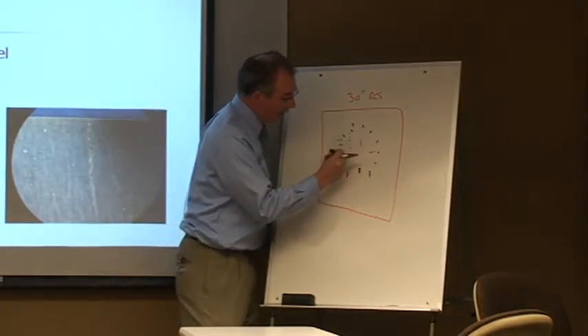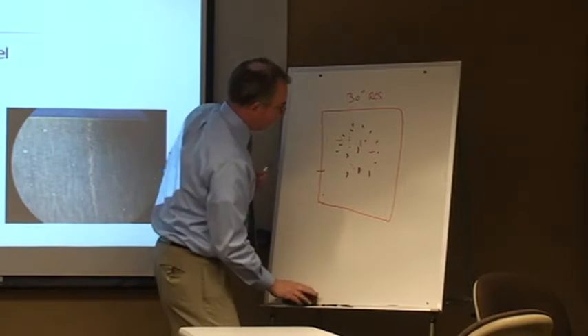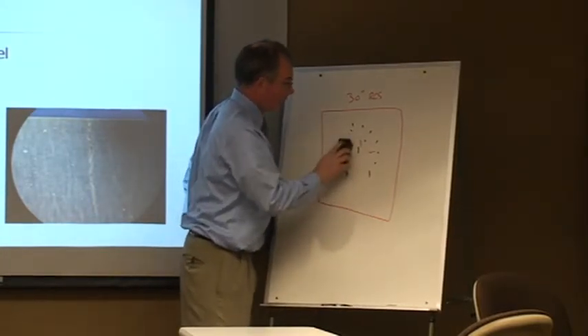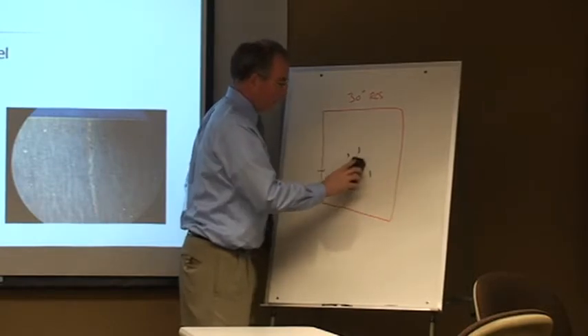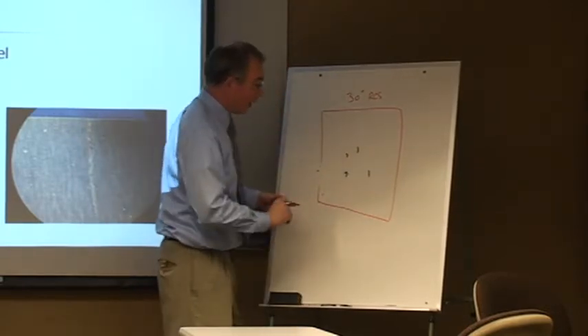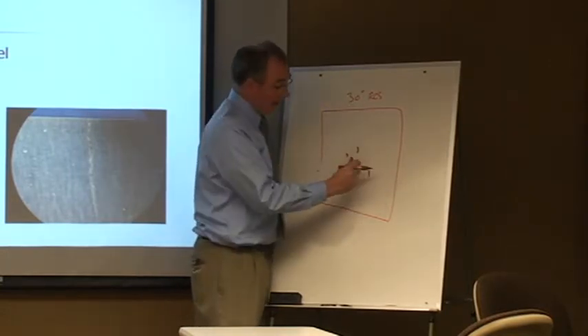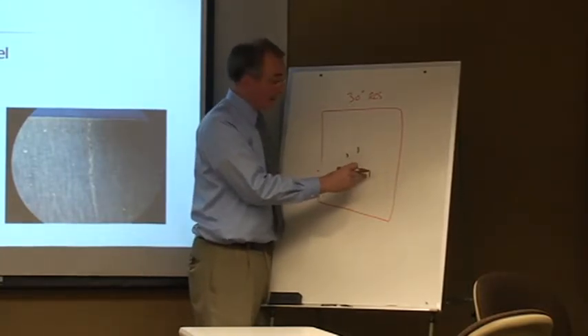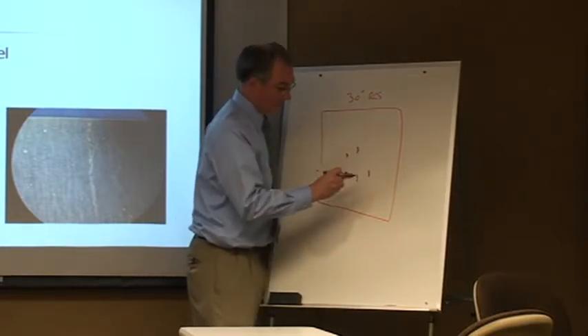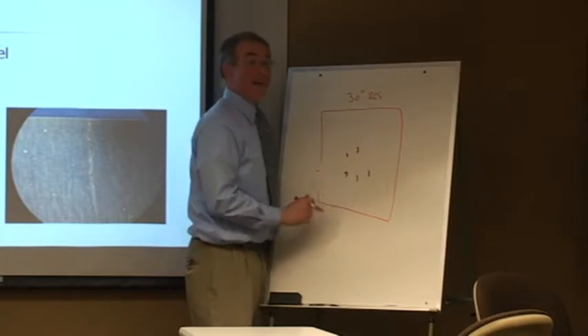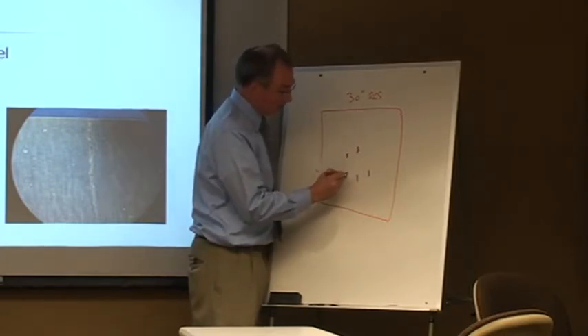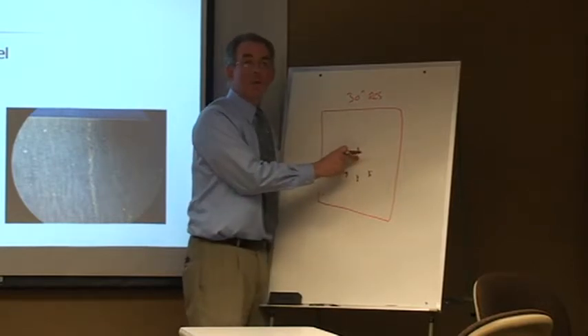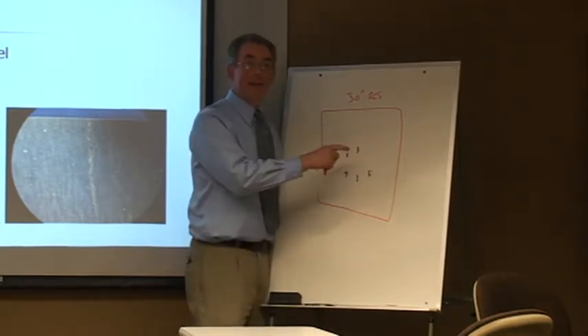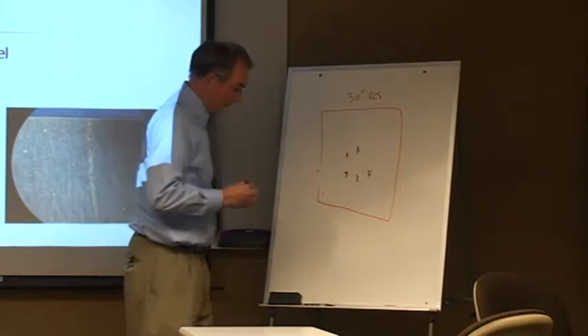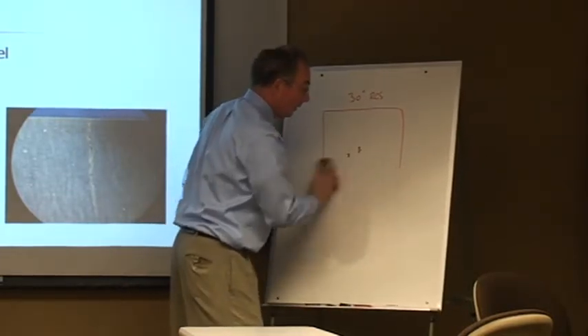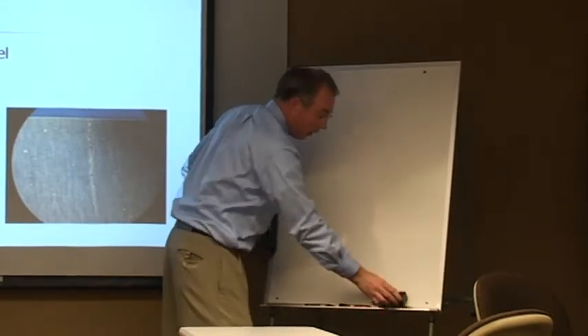So now, if I add my sulfides, and just to oversimplify, if I have 10 atoms, instead of having 10 atoms accumulate at one sulfide, that way I don't have to get fractional. If I have 5 manganese sulfides, well, maybe I end up with 2 at each. So I would rather have 2 at 5 of these than 10 at one of these. The stress is going to be much less. Okay? So anyway, that is what can cause hydrogen flake.